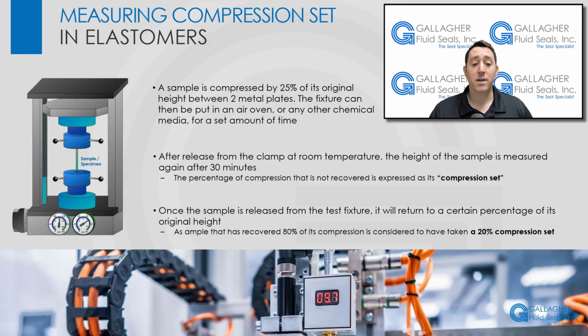When measuring compression set resistance, the sample to be tested is compressed by 25% of its original height between two metal plates. The fixture can then be put in an air oven or any other chemical media for a set amount of time. Normally, the standard test is 70 hours. After release from the clamp at room temperature, the height of the sample is again measured after 30 minutes. The percentage of compression that is not recovered is expressed as its compression set.